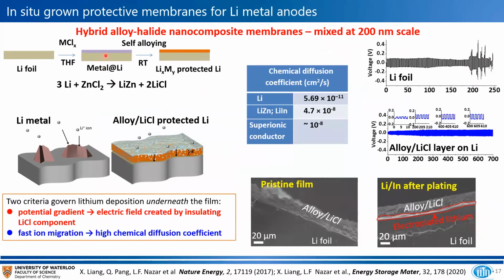And we developed an in situ approach where effectively metal chlorides react directly with lithium metal to form an alloy. And the reaction here is shown for the reaction of lithium metal with zinc chloride to form lithium zinc. It works really well with indium. And so the point is that this film forms directly on the lithium metal. And the diffusion coefficients of lithium in these alloys are basically the same as that of a superionic conductor. And lithium chloride is formed as a byproduct, which basically increases the electric resistance of the film and allows the potential gradient to develop, which is what's necessary to drive lithium deposition under the film.